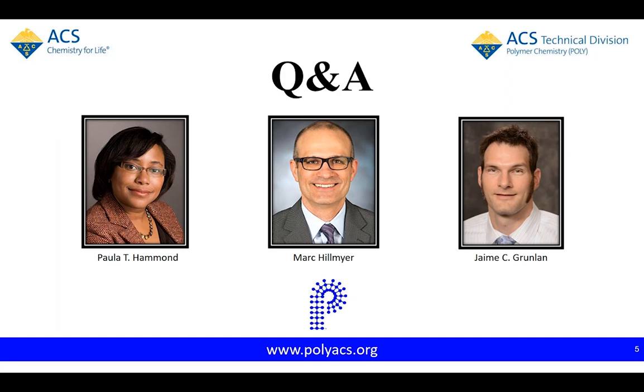And so the way the chemistry of the coating interacts with those different fiber chemistries makes it much more challenging, because I'm trying to fight off two different chemistries at the same time. It's often very difficult, but you saw that with layer by layer, I can mix and match chemistries to do two things at the same time. Paula showed the same thing, of course, with her drug delivery. You can compartmentalize things, you can put multiple components in. It's very mix and match.